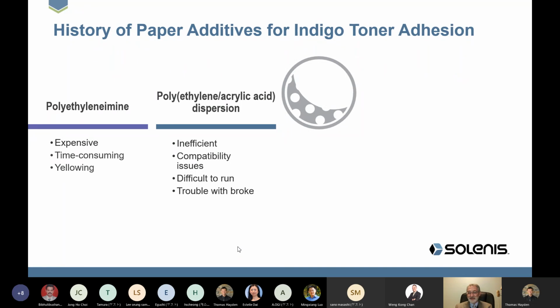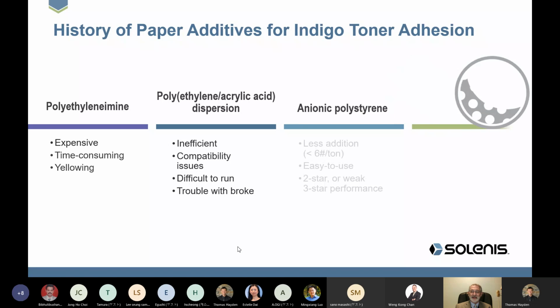I put the little golf ball image on the top there, just as a reminder also that when you're adding an anionic emulsion of a material like ethylene acrylic acid, it's the same chemistry that's used to make golf ball covers. So if you mix that polymer with something like a calcium salt or an aluminum salt or any other multivalent ion, you will form a very, very tough deposit that will be very difficult to remove from your paper machine. And so one has to be very careful when running the polyethylene acrylic acid dispersions at a size press.